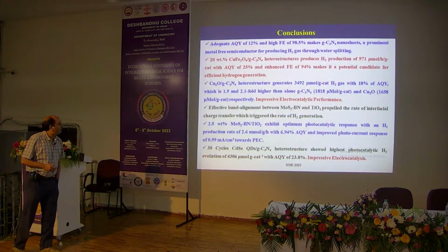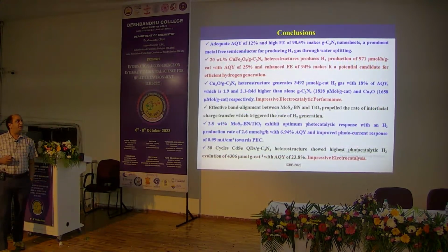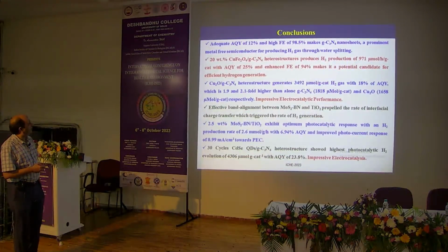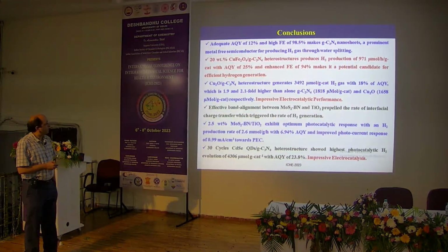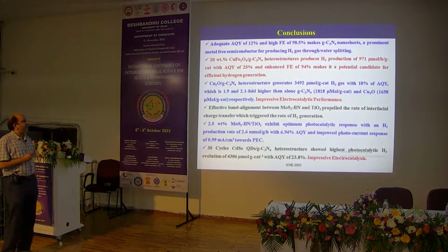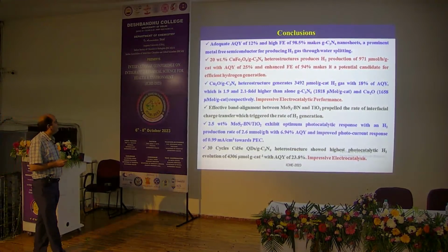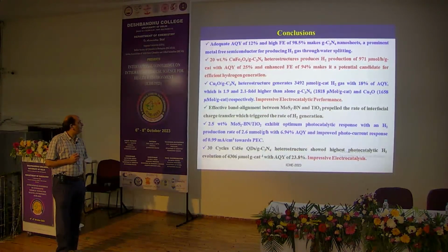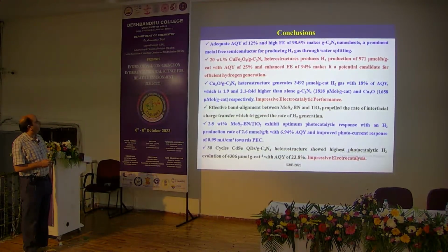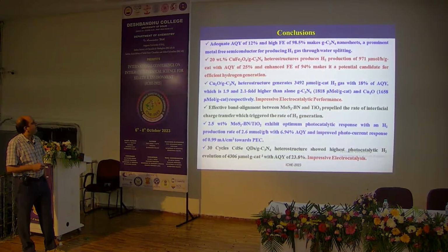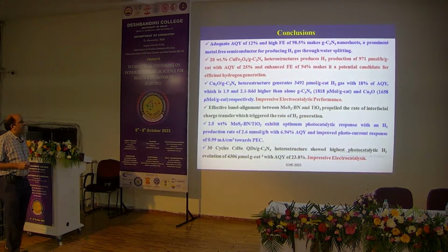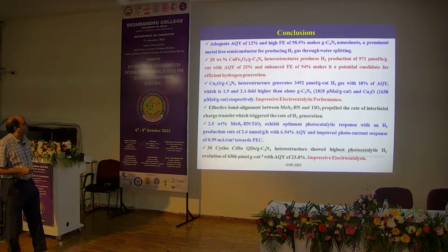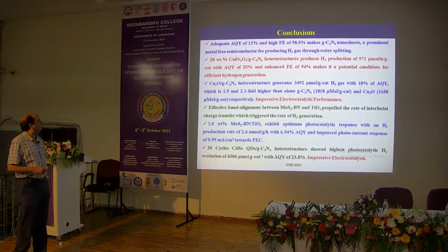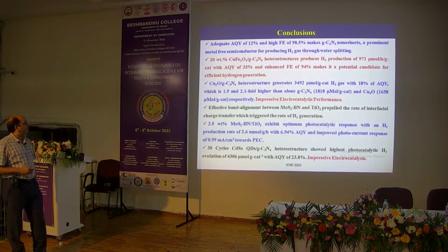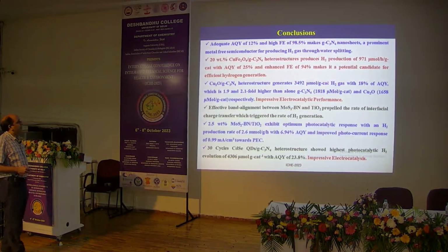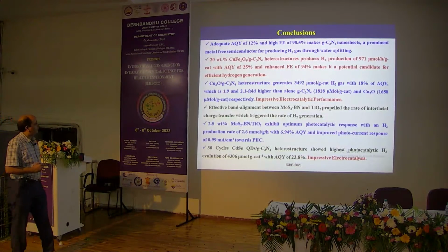Now coming to the conclusion, we have obtained an adequate apparent quantum yield of nearly 12% and high Faradaic efficiency, which is around 99%, which makes graphitic carbon nitride nanosheets a prominent metal free semiconductor to produce hydrogen. And the 20 wt.% copper ferrite over graphitic carbon nitride heterostructures could produce hydrogen of around 970 micromole per hour per gram with an apparent quantum yield of 25% and high Faradaic efficiency of 94%, which makes it a potential candidate for efficient hydrogen generation.